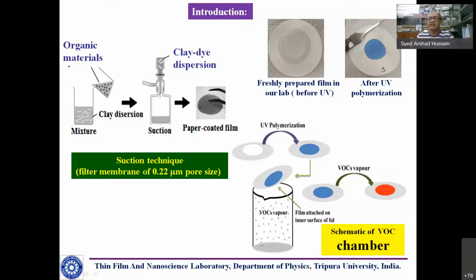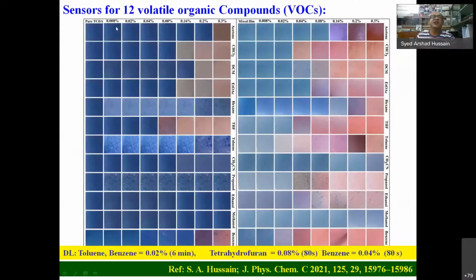Then for the VOC sensor, it's a self-prepared system. We made a lid on a simple beaker, and inside the lid we put this blue film. Okay, and we kept VOC here in different volume ratios, and with time we see that the color changes. It converted into red. You can see we tried with 12 different VOCs. Okay, toluene, benzene, in this way, say DMSO, hexane, THF, so many, propanol, ethanol, methanol, etc. So we tried as a whole 12 different organic compounds, and we found that almost all these compounds respond, our sensor responds to all these components. But of course, the response depends on the concentration of the analyte as well as exposure time. So one has to play with these things to have a real sensor. But the good thing is that it responded.